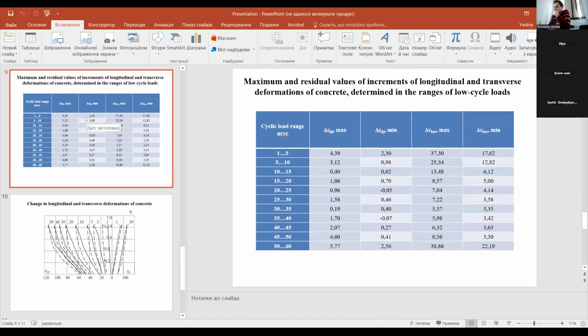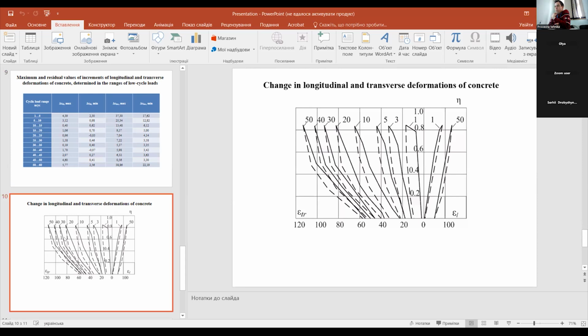The low-cycle fatigue of concrete obtained from the dependency represents a hyperbolic curve in the coordinate axes: stress level eta cycle, and number of loading cycles n sustained by the sample until failure. Maximum and residual values of longitudinal and transverse deformation increments of concrete were determined for the range of low cycling loads. Changes in longitudinal and transverse deformation of concrete are presented.